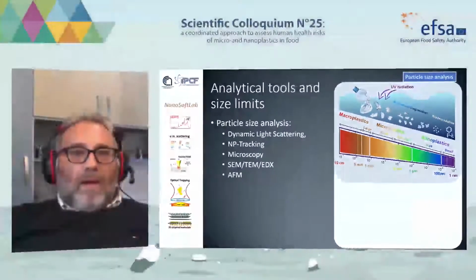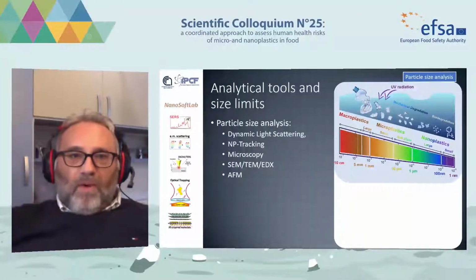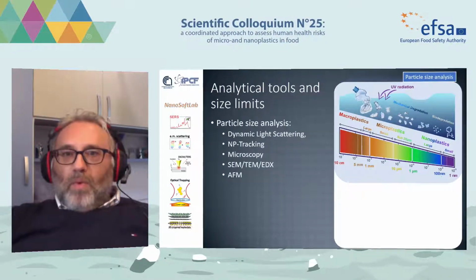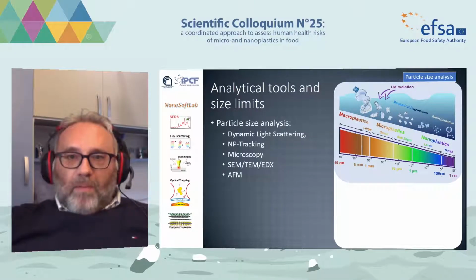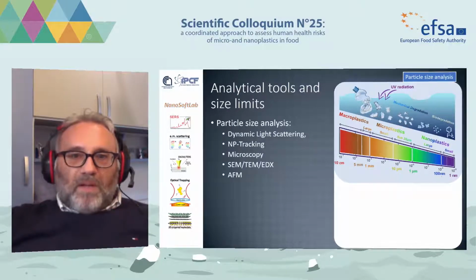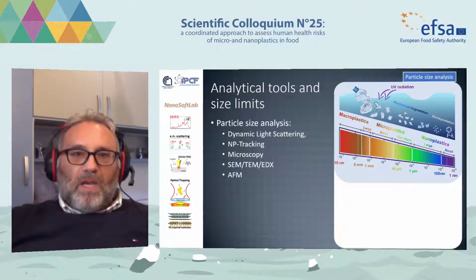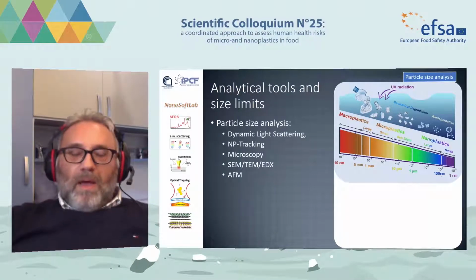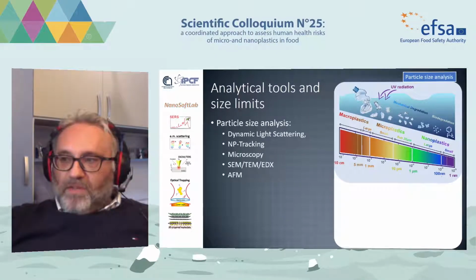Okay, so basically we are fully covered for what concerns the particle size analysis. So we can monitor particles going from 10 centimeters to 1 nanometer using dynamic light scattering, nanoparticle tracking, optical microscopy, electron microscopy, atomic force microscopy.